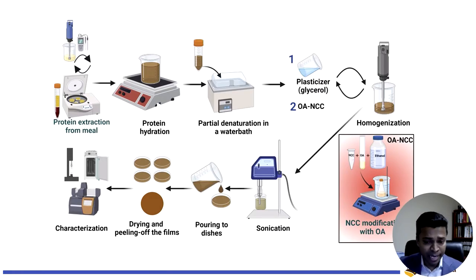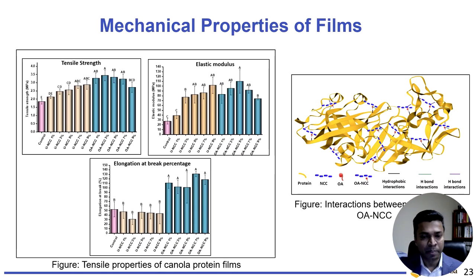And then we used the same method to prepare the films. With the film preparation, we observed some unique results. Tensile strength increases with the addition of the oleic acid grafted nanomaterials compared to the control, which is a good thing. But at the same time, the elastic modulus is not increasing in the same way compared to the previous study. In fact, when we increase the tensile strength, the elastic modulus stays almost similar without much change, much better than the control sample.